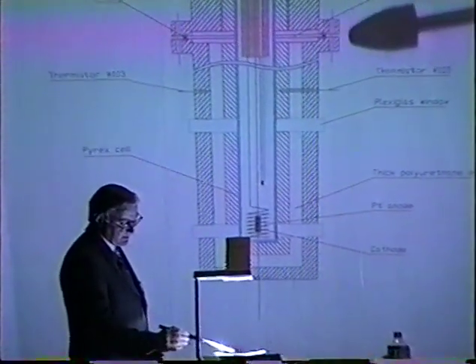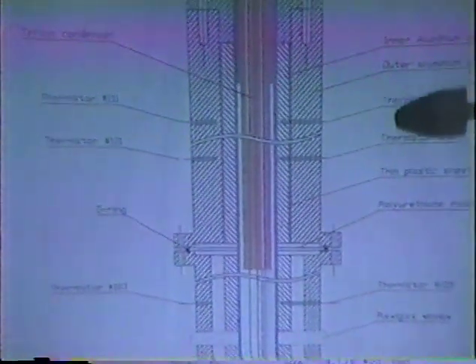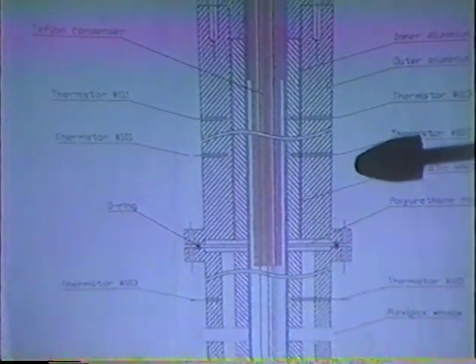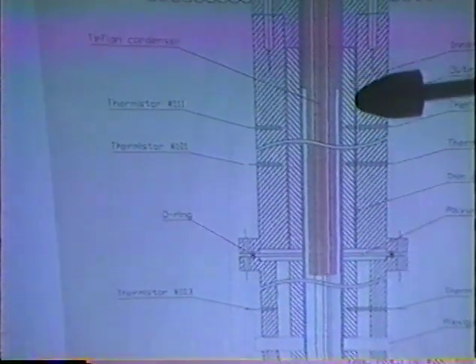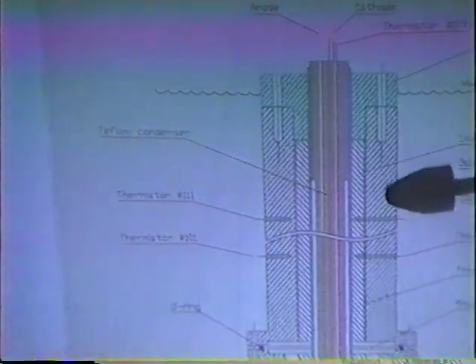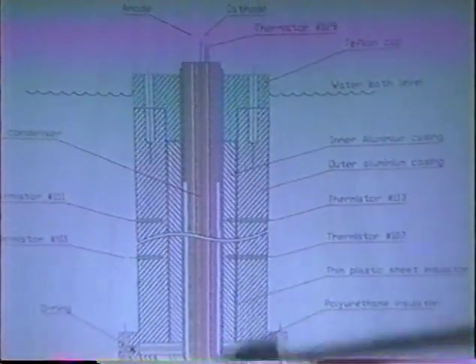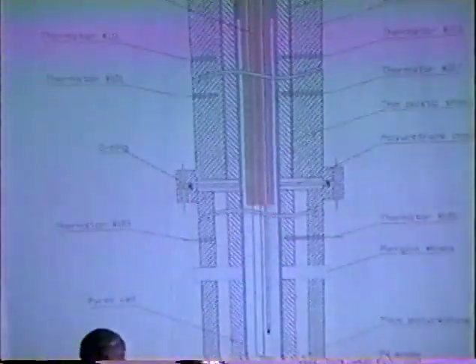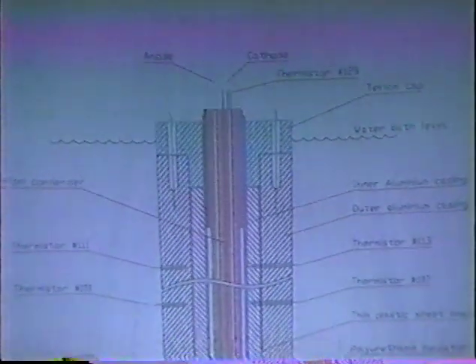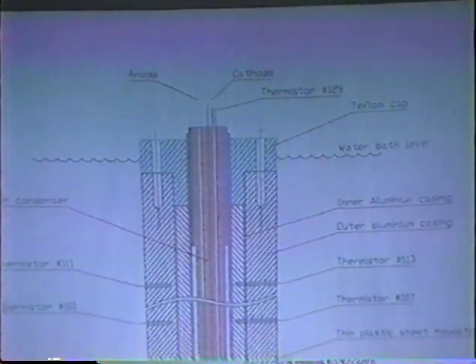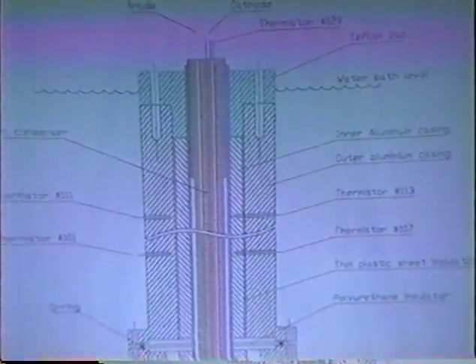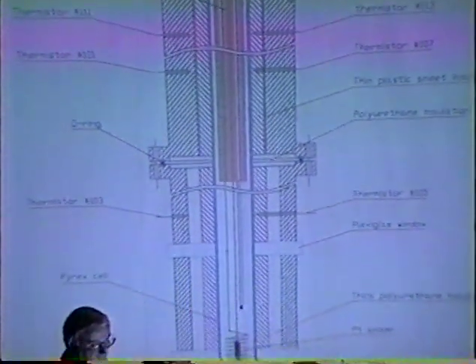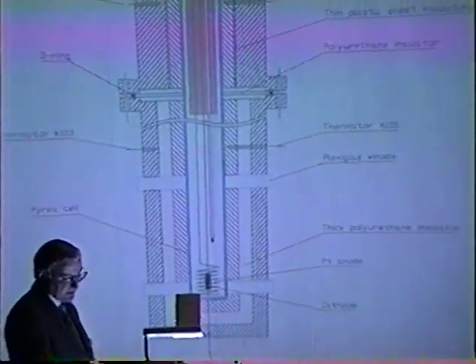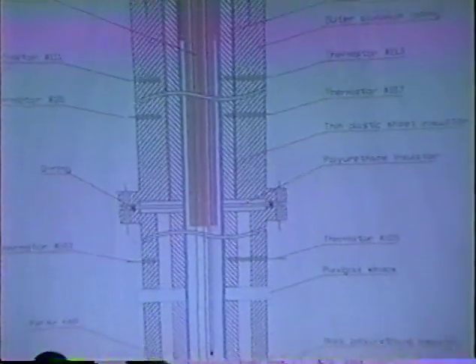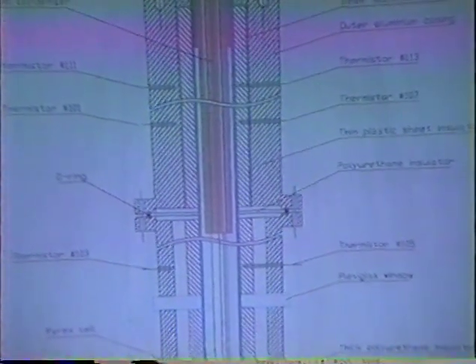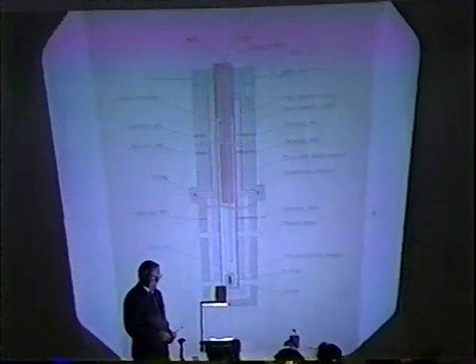You can change similarly in the upper section, which we'll call the measurement section or the distillation or condensing section. It's essentially the same construction, except normally you have a thinner layer which gives rise to a higher heat transfer coefficient, and therefore you're able to condense the boiling liquid, or the hot liquid, and retain most of the cell contents, which of course will condense back down at the bottom. So we have no evaporative losses, at least up to the boiling point. Again, that depends on the total power input. The early calorimeter which we built was stable up to about 100 to 150 watts. They've now been somewhat redesigned, made a little bit larger, and with different thermal transfer characteristics, we're able to calibrate these up on the order of 350 to 400 watts.